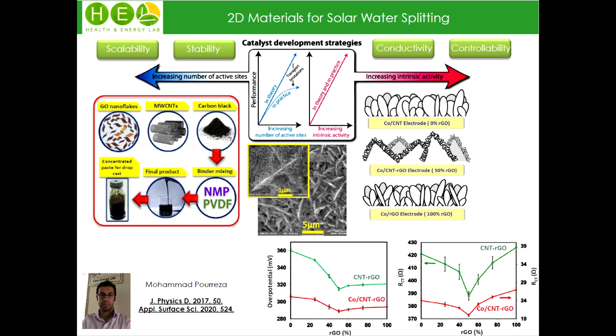In the next step, we tried to produce a hierarchical structure to maximize the available surface area. So we benefited from electrochemically reduced graphene oxide, and we provided a mixed paste with CNTs and some binders. We tuned the composition of this paste and applied it as a host for the next step, which was electrodeposition of cobalt oxide flakes.